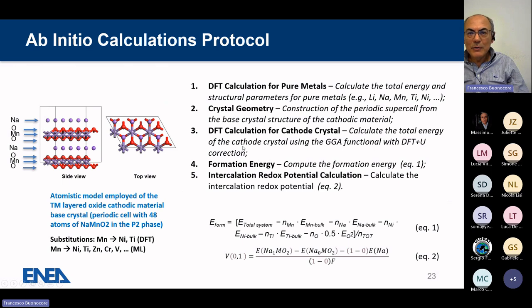So we defined an ab initio protocol for our calculations. These are the typical crystals that we used to screen the crystals with our graph neural network. And this is a manganese oxide with intercalated sodium ions. We explore all the possible configurations by substituting nickel and titanium to manganese, searching for the most stable system, as I told you several times. So we defined this protocol for our workflow.